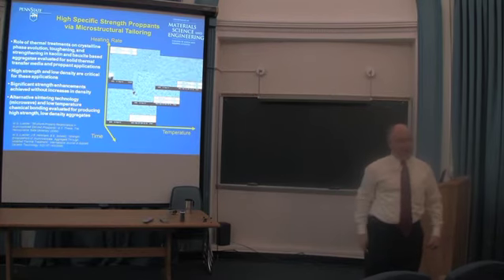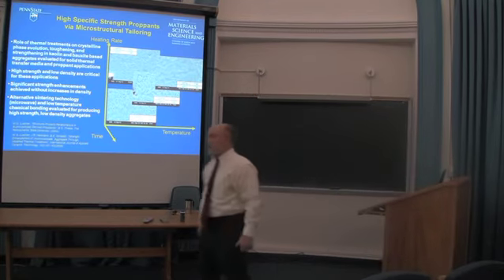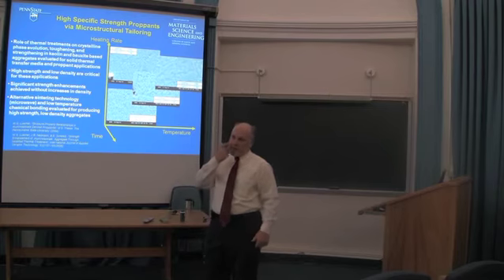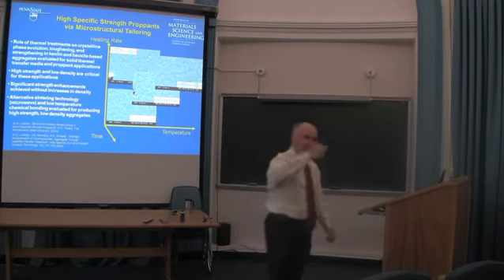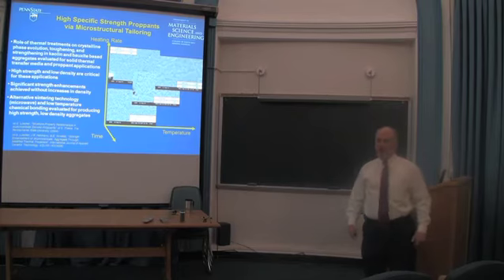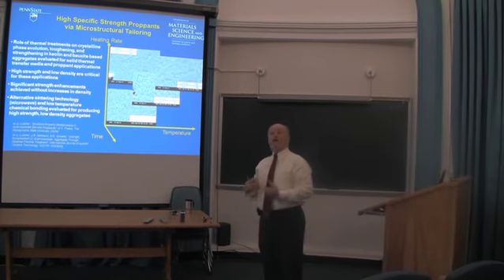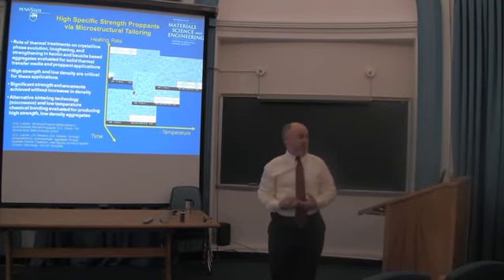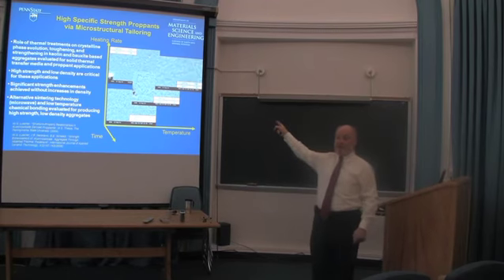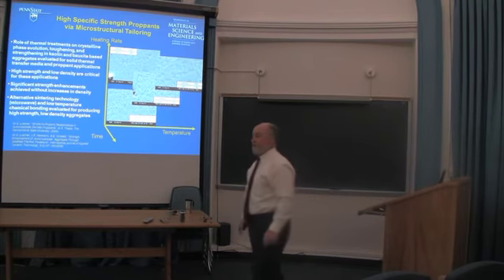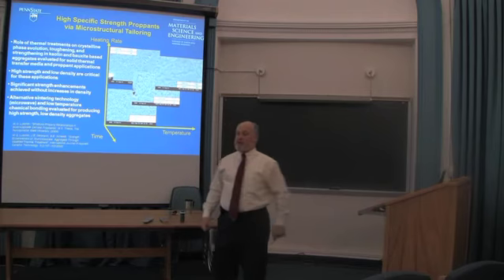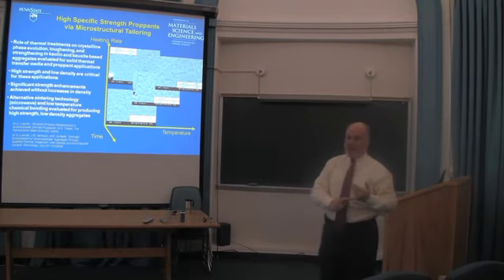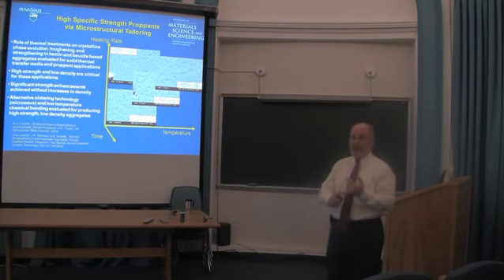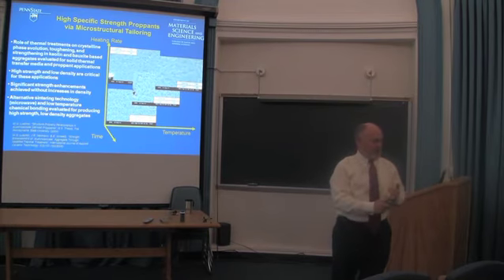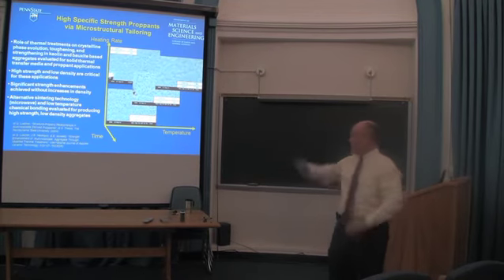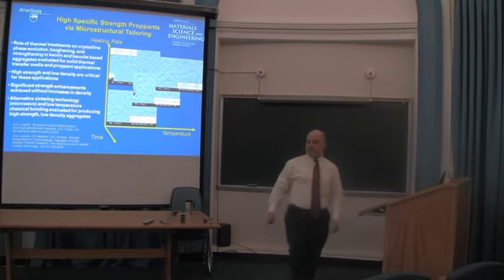Why'd you choose those? Because we went to Arnulf Muan's phase diagrams and we said, the steel industry says that if you have this in your refractory, you're going to have these kinds of reactions that, for the purposes of refractory, are undesirable, but for the purposes of densification by a liquid phase, are everything you want. And you add two additional process parameters: the composition of your dopant, how much you put in, and what your oxygen partial pressure is while you're sintering these things, give you different microstructures. Okay?